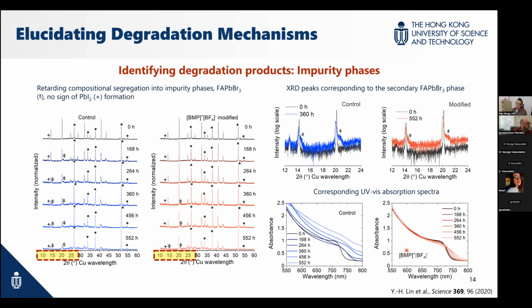So what does that mean? It means those ingredients, those components can give rise to narrower band gap coming out of the materials. So it becomes redshifted. And this is evidence to corroborate what we found in this XRD measurement. So when adding this kind of additive, we retard this kind of mechanism from occurring.